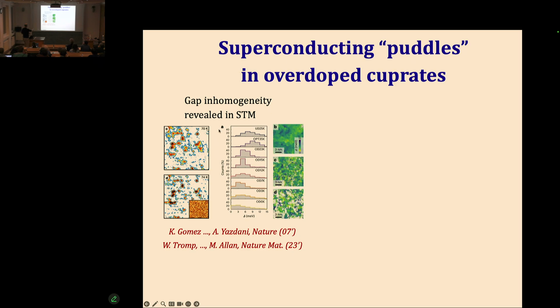But if you do STM, you see that the gap feature in the spectrum that you associate with superconductivity is not actually zero everywhere. In this color map, white means no gap, that means constant density of states at the Fermi level, and these red patches are regions where locally the gap is finite. You see these little islands which seem to maintain their superconducting gap even above TC. The size of these regions is quite small, a few nanometers. There's no scale here, unfortunately, but the size of this thing is 3-4 nanometers.